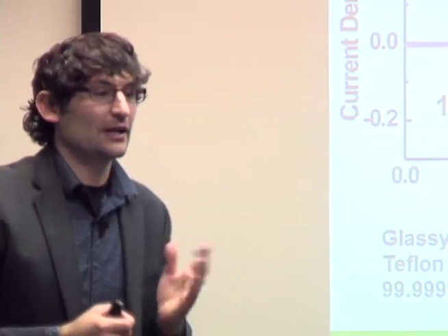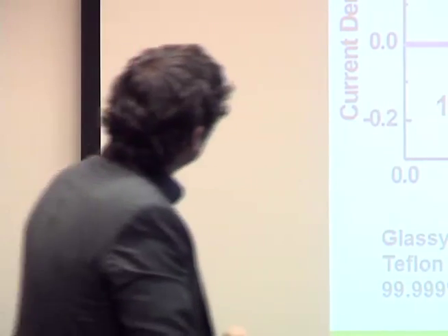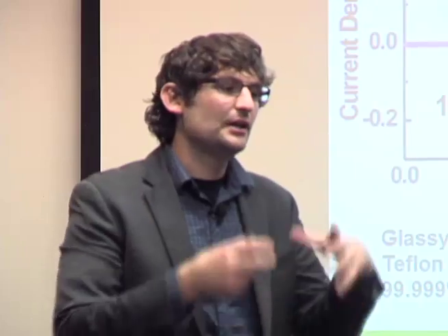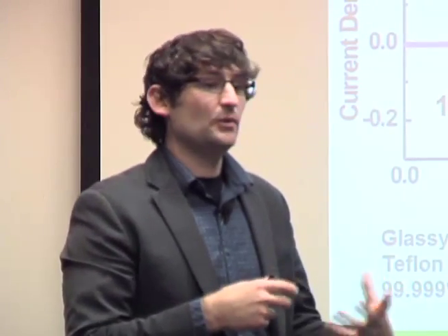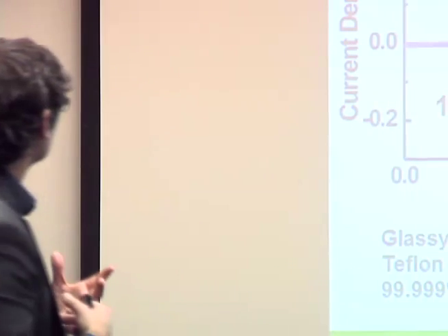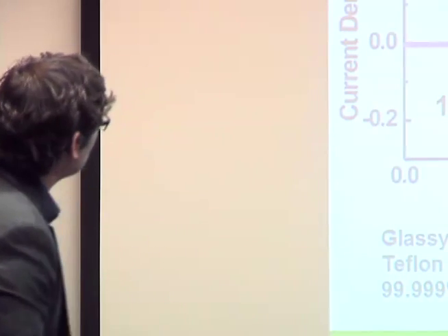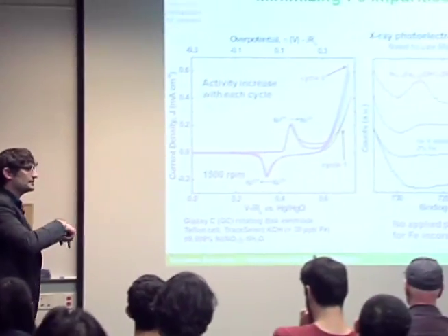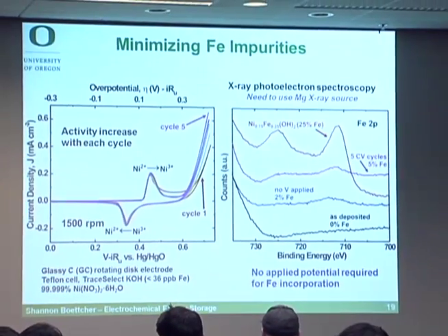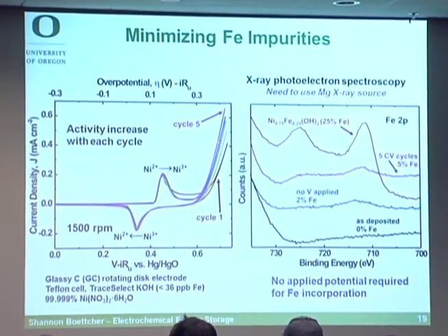Okay, so the first thing we had to figure out was how to actually get rid of the iron that was coming in unintentionally from the electrolyte. And so when I saw this data, it really blew me away. So we took a glassy carbon rotating disc electrode, really clean, freshly polished, Teflon cell, no glass parts anywhere. Glass has iron in it. It's etched by KOH. You get rid of all your glass. We used the highest purity metal salts and the best KOH, analytical grade KOH you can buy. And you put a nickel hydroxide film on an electrode, and you cycle it. And it's a rotating disc electrode, so you're stirring. And what you find is every cycle, the activity increases.